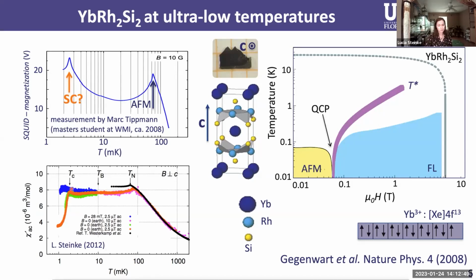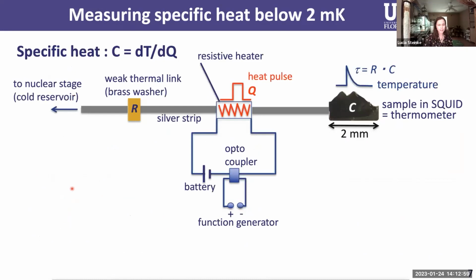Another experimental probe that we can employ to find out about this is measuring specific heat. That could give us an idea of how many states are involved in this phase transition. So we also did that in this temperature range. And the basic idea to measure specific heat, so the response to heat of the sample, is very simple. You apply a heat pulse, and then you watch the thermal relaxation, and from the time constant, you can extract a specific heat. But one thing that you already see in this setup is we had to play a few extra tricks because things aren't quite as simple at ultra low temperatures.